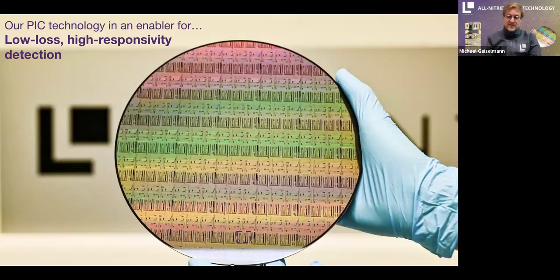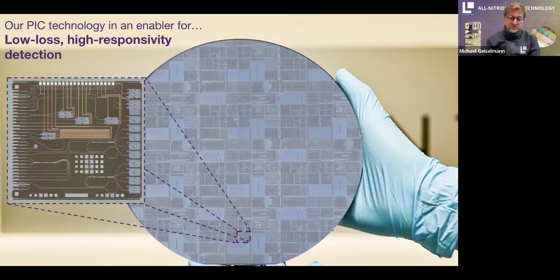But modulation is not the only thing that is needed in a photonic integrated circuit. You also need for many applications detection, and here we took a different integration approach to get PDs integrated also on a wafer scale level. And so here you see again a 200 millimeter wafer with integrated PDs. So the photodetectors are sitting here on the right hand side of that photonic integrated circuit, and here you actually can see nicely this local cladding opening, and then that tiny golden dot, that's the photodetector and the contacts.